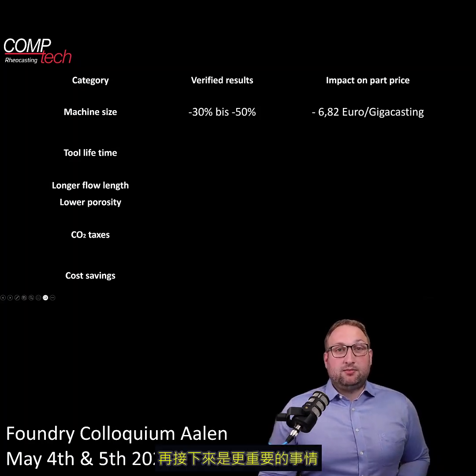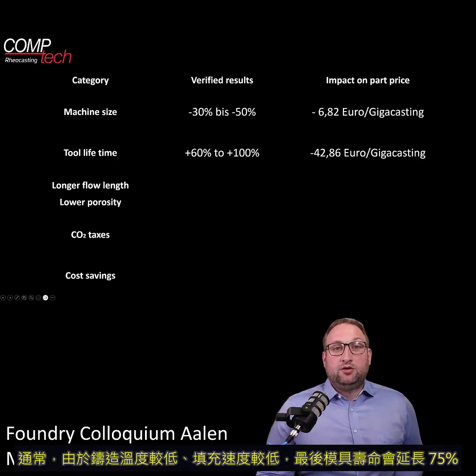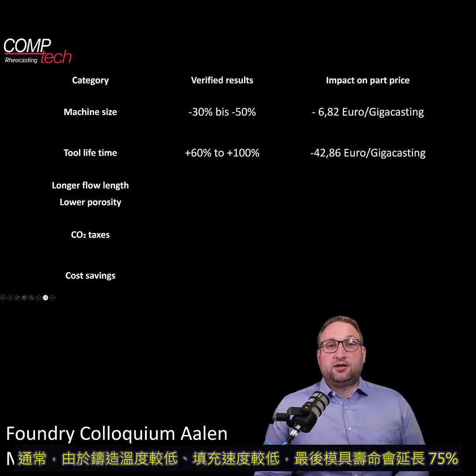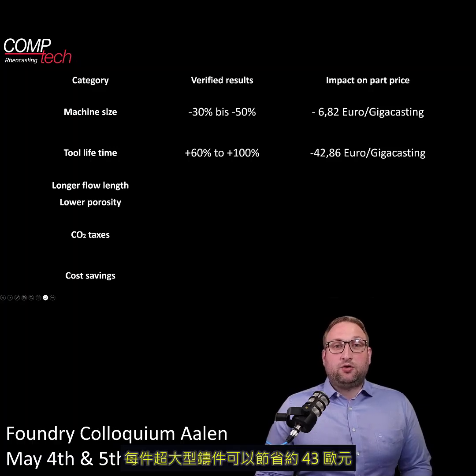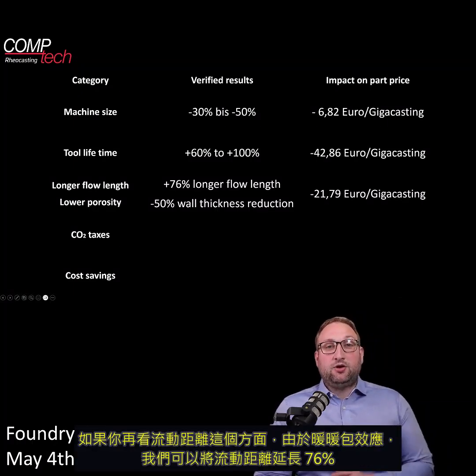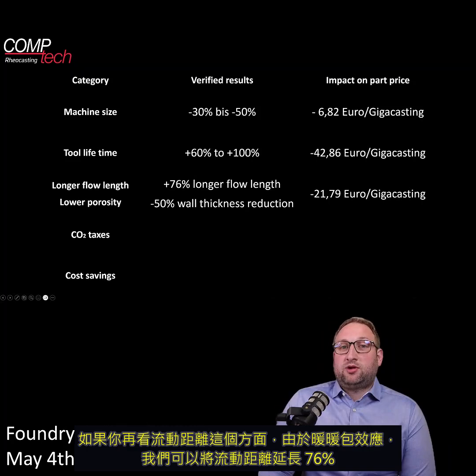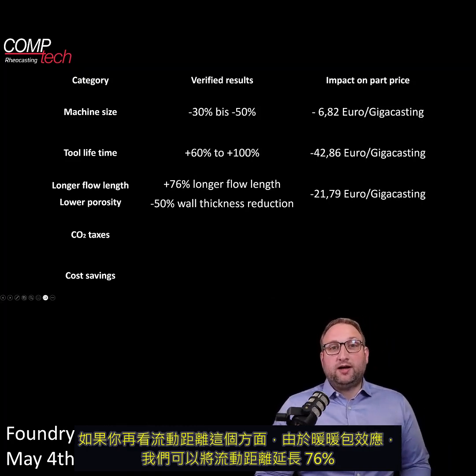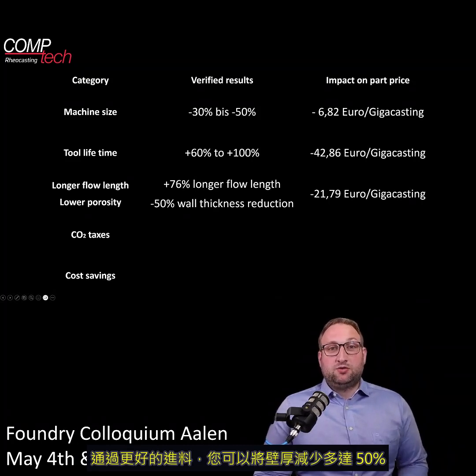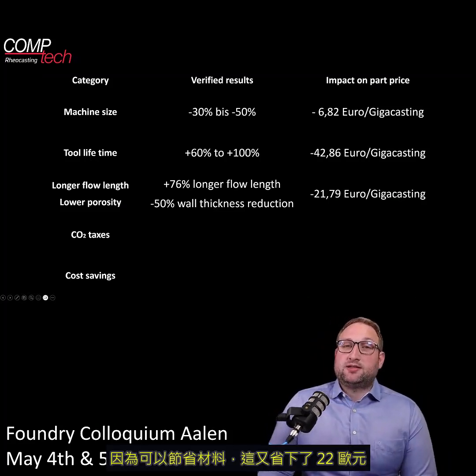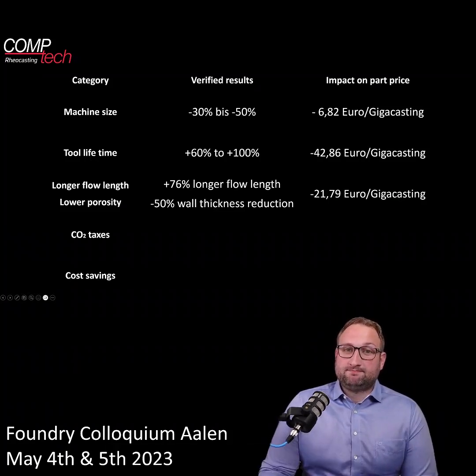The next thing is the major thing. Usually we end up with 70%, 75% longer die lifetime due to colder temperature and lower speeds. This is about €43 per giga casting in savings. If you look at the longer flow length, we can reach up to 76% longer flow length due to the pocket warmer effect. And with better feeding, you can reduce the wall thickness up to 50%. With the material saving, that's another €22.